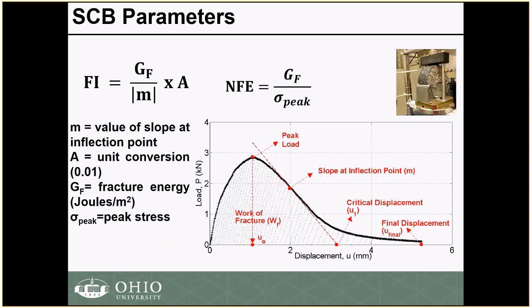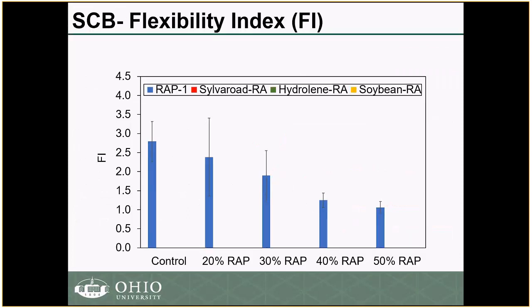Another parameter that we have recommended, based on a study conducted back in 2017 for Illinois DOT, was the normalized fracture energy. It's the fracture energy divided by the peak stress, or the strength that is obtained in the SCB test. I'm showing here the flexibility index, and a very important thing to note is that these numbers are for long-term aging, and the aging was done by putting the prepared mixtures for 5 days at 85 degrees Celsius.